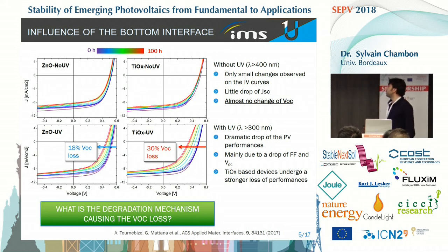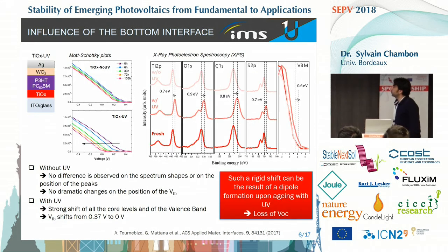So we decided to go a bit further and tried to identify the degradation mechanism causing this VOC loss. First, we focused on titanium oxide-based devices, and we did some CV analysis and extracted the flat band potential of the devices along aging, without UV and with UV. When you cut the UV, we have just a small change of the flat band potential. But as soon as you have some UV present during the aging condition, you have a strong shift of the flat band potential.